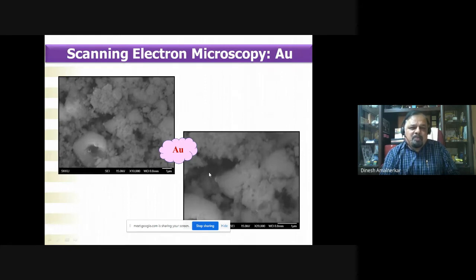On the contrary, for SEM or FESEM analysis, if the material is insulating or semiconducting, we need to put a gold or silver coating on it to avoid charging. Here, it was the other way around. We could not get rid of charging in this particular case. What I have seen here is maybe nanoscale gold, a combination of spherical particles and some distorted faceted particles, embedded in an insulating matrix, and this insulating matrix might be creating a kind of charging phenomenon within our sample.